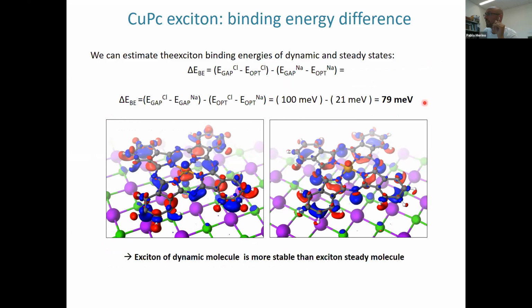And what we found is that there is a 79 milli-electron volts difference, which tells us that the exciton of the dynamic molecule is more stable than the exciton of the steady molecule.